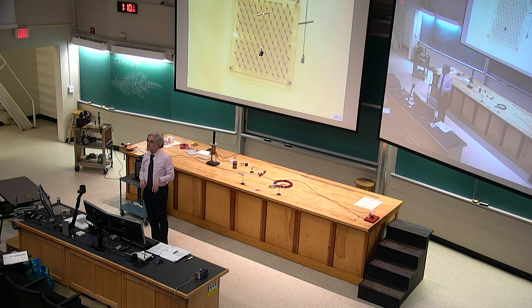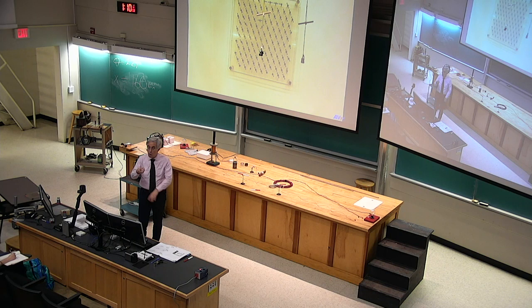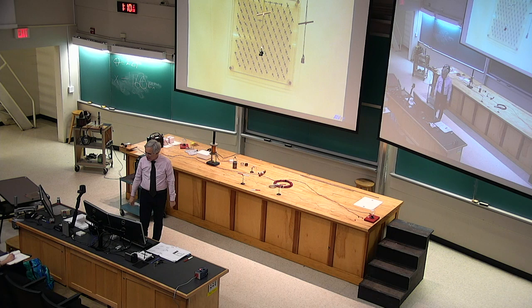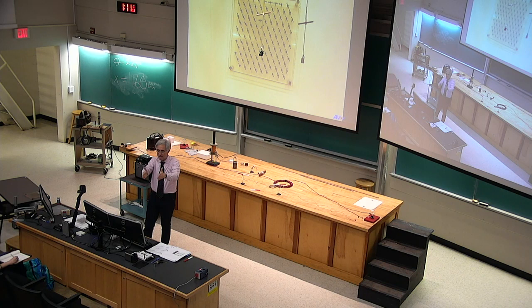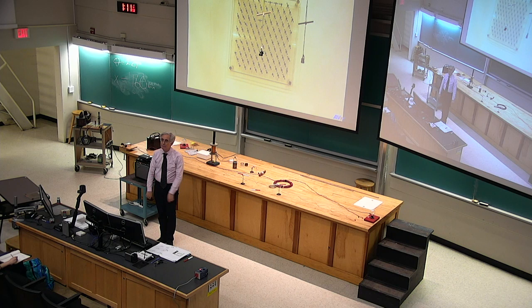The domains aligned so that they point their south pole toward my approaching north pole — they're happy and attracted. All the other ones begin to evolve such that they also point their south poles toward my approaching north pole. Technically, the domains don't rotate as a team; they change in size. One domain aligned the right way grows — its domain wall moves and gobbles up adjacent improperly oriented domains until finally all the domains are pointing the right way.